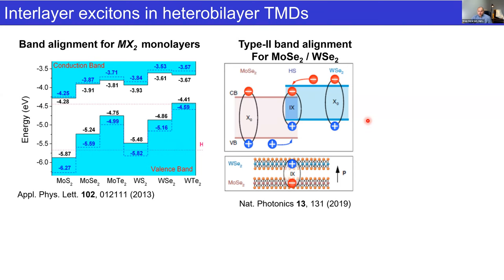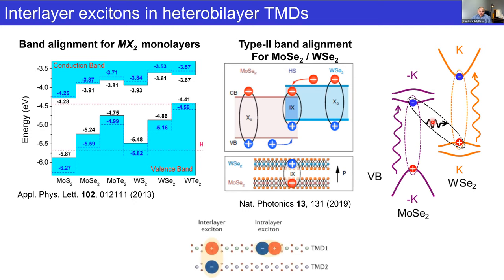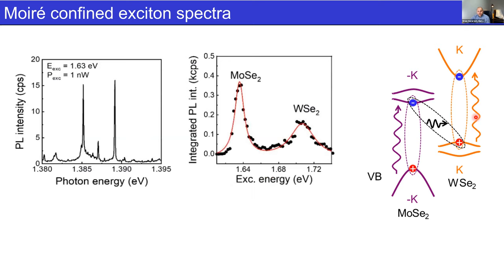And so in our experiments today, we'll be talking about both interlayer excitons, which we observe in photoluminescence, or intralayer excitons, which are basically the intrinsic A excitons of each independent layer, that we can probe in absorption, basically using resonant reflectivity. So if we look in photoluminescence, we can do a PLE type experiment. So we can excite across either the molybdenum diselenide or the tungsten diselenide, and then look at the interlayer exciton emission. And we see these sharp peaks arise as we hit one or the other resonance.